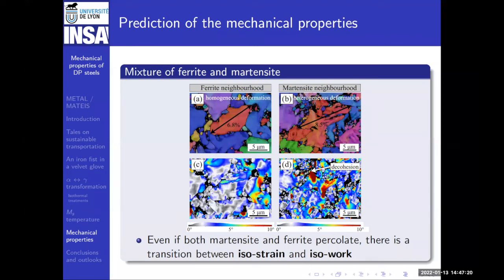So imagine you have two percolating phases, one hard, one soft. For low deformation, let's say that they are both deforming the same way, isostrain. But above a threshold value, martensite starts to break. So we are slowly going from isostrain to isowork. And this is what is new here.